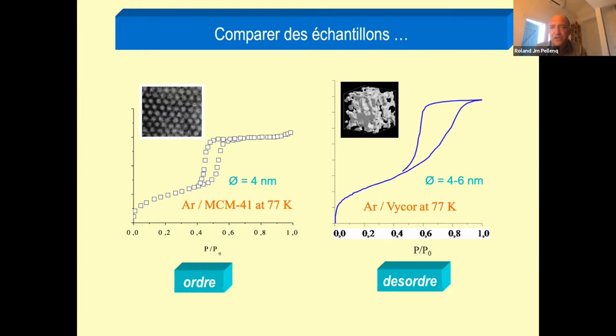There are good reasons for that. The desorption line is actually at equilibrium—it follows the Kelvin equation. The adsorption line in Vycor shows that you have different environments, so there's a gradual filling up of the pores: condensation in some parts, no condensation in others. At the end you get this smooth signal on the way up, but on the way down, the desorption corresponds to the Kelvin equation.